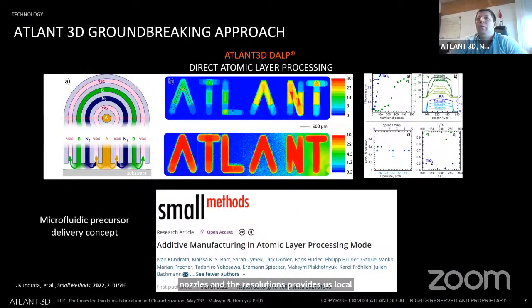And here you could see our first article, published in 22, where each letter was deposited with different thicknesses. As you could see, a lot of artifacts at that time. We already fixed many of them. And what we didn't expect is conformal and also very abrupt deposition, as you could see here from the lines of the process. And this basically gave us the possibility to control at atomic level each material and obtain patterns of any shape.